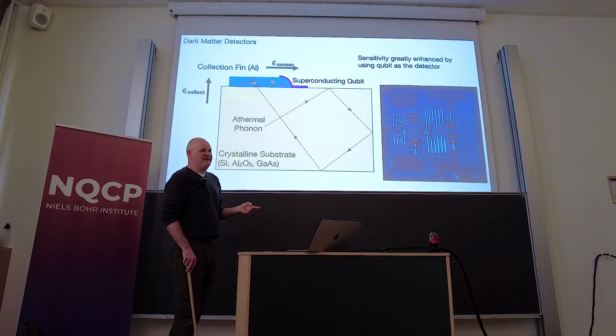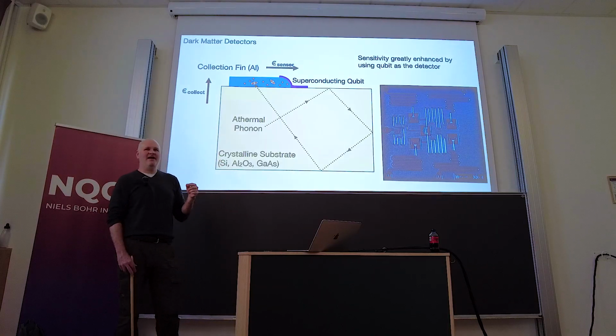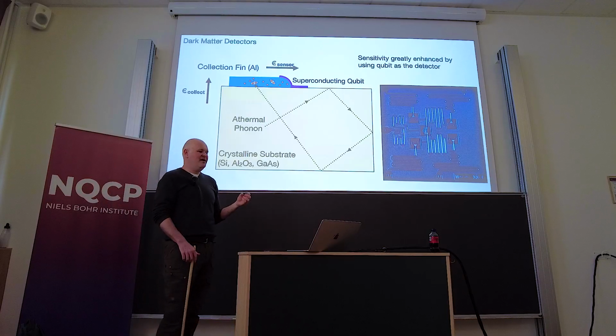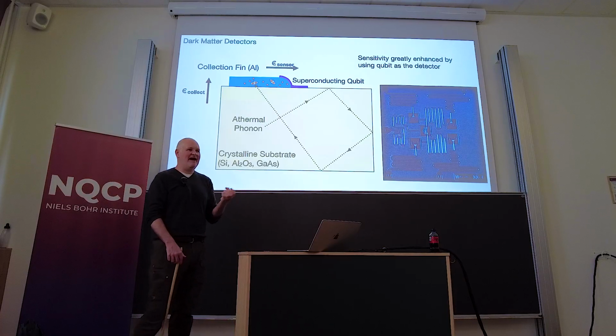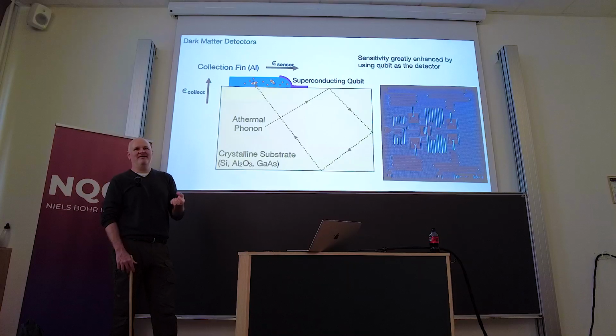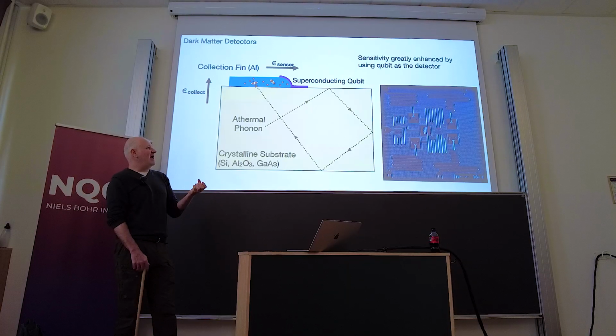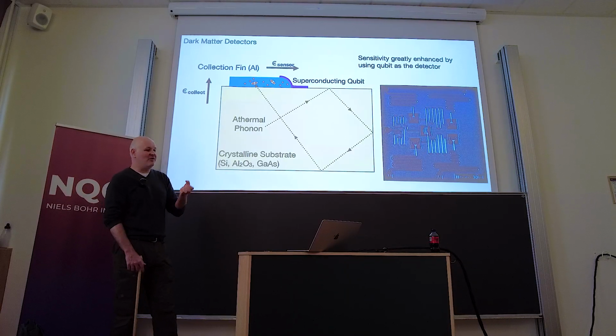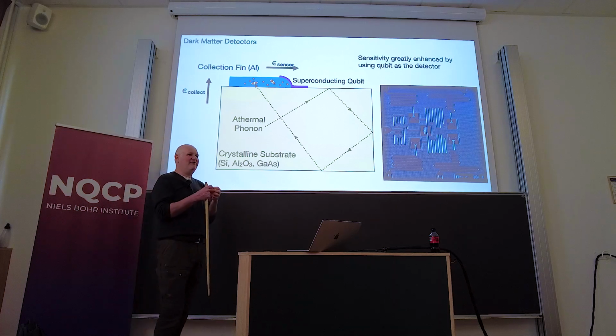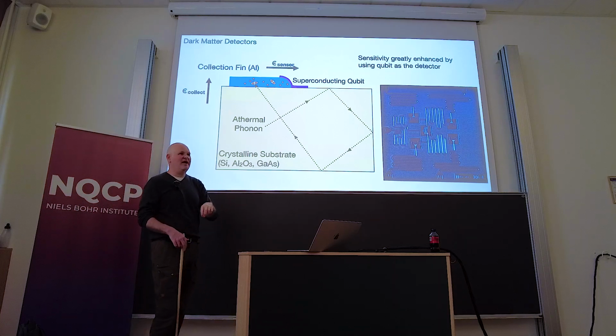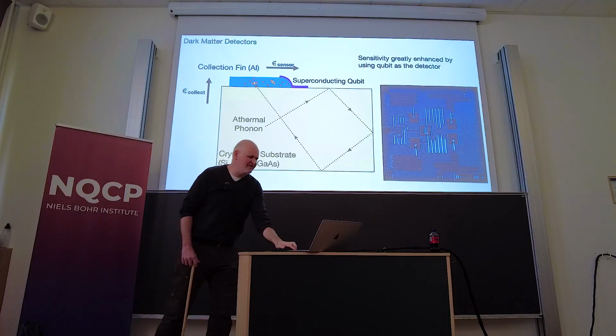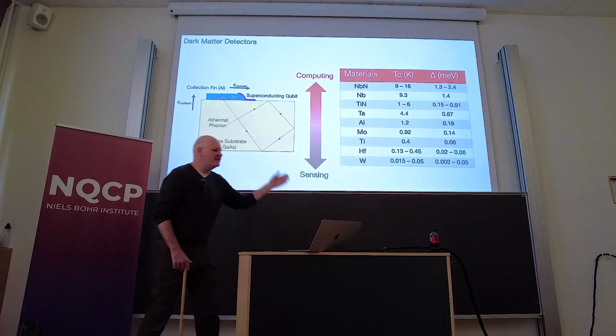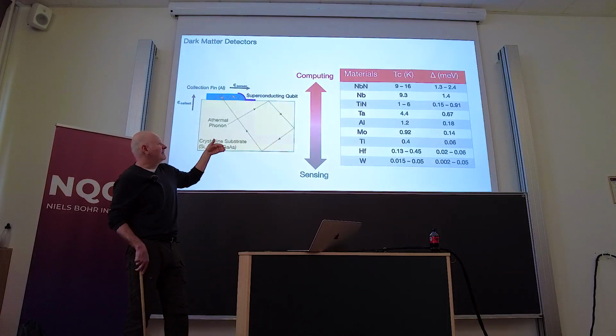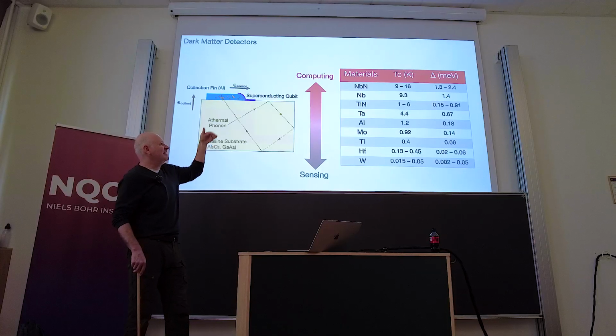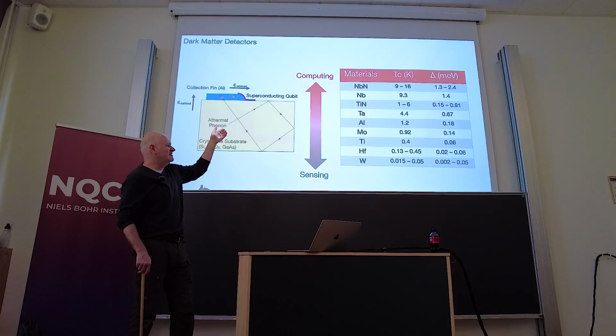But there's a better way of doing this, which is rather than just having a superconductor that then loses its superconductivity, you actually build essentially a really bad qubit. And you put that qubit on the collector, and when a phonon interacts with the qubit, it's even more sensitive and gives you even more feedback than just breaking of Cooper pairs. And I've kind of already said this, but essentially there's this correlation where on the computing side, you would like to push perhaps slightly more to the higher TC, on the sensing side, the lower TC.